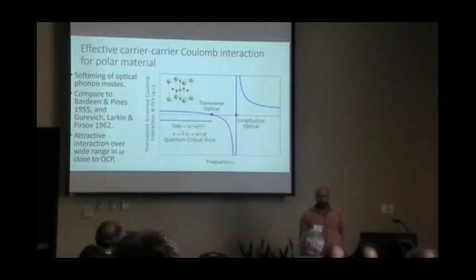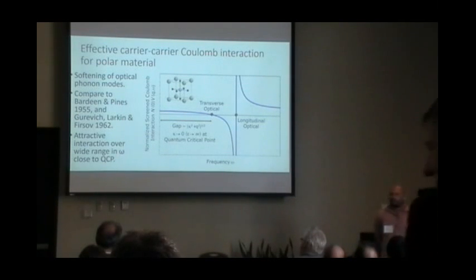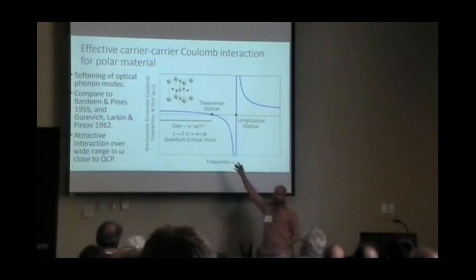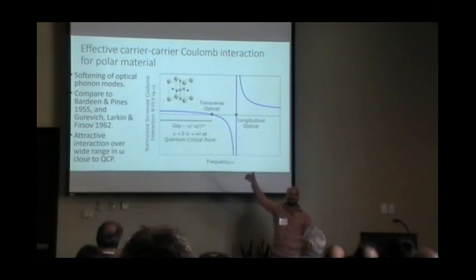So you can see now if you soften the transverse optical modes, they will go to 0. Actually, you will get huge areas of an attractive interaction for low frequency. Actually, in the most extreme case, you would even get a static extreme attractive interaction.